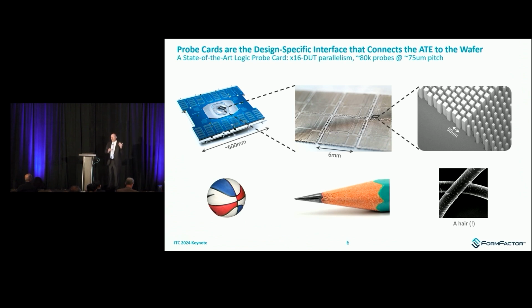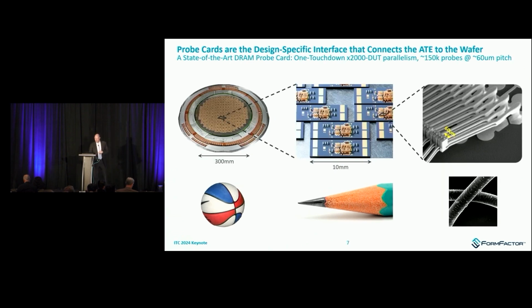When we look at where things were 50-odd years ago, we were nowhere close to this. You had maybe 5,000 probes per probe card, which was considered a big card. But the drive for complexity, more complex die, higher performance die, and then lower cost of test, so higher parallelism, because that's by far the key driver of lowering cost of test, you see some pretty significant increases in complexity. So that's logic state of the art.